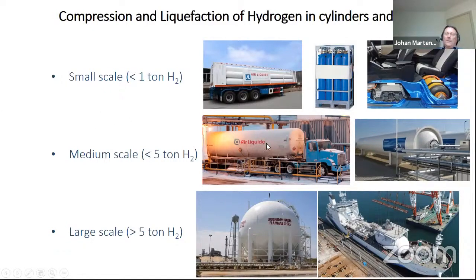The medium scale and the larger scale, typically it's liquefied hydrogen, and the liquefaction of hydrogen is done at very low temperatures. You need minus 253 degrees C. So that's even more energy demanding. You lose something like 40% of the energy that is contained in the stored vessel by simply the request for cooling that deeply. Ships are being constructed for transporting liquid hydrogen, but there's really a gap in the technology today.